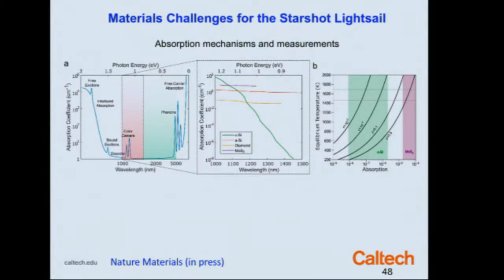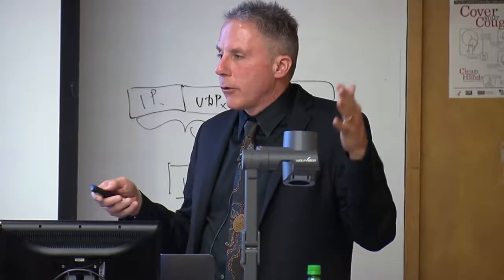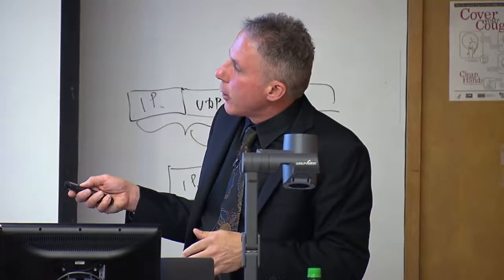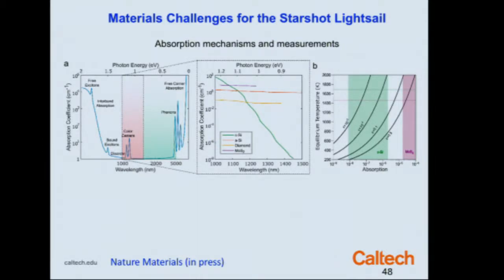So what we need is to have materials that have very, very low absorption coefficient. So this is the absorption coefficient in inverse centimeters of materials that we found data for: molybdenum disulfide, amorphous silicon, crystalline silicon, or diamond, and here crystalline silicon. And then we also need to have very low absorption at the pump laser wavelength, right about here. But we also can't have a lossless material here because we have to have some emissivity. I talked about the balance between absorption and emission yesterday. We have to have a material that has finite emittance. So we need to have some emittance, some absorption here at long wavelengths outside the pump laser wavelength band, such that we can use blackbody radiation to cool the sail. That turns out to be very important.